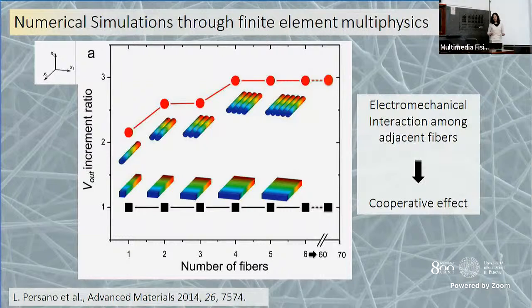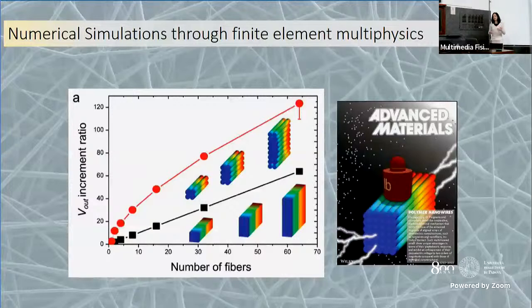And this can be explained as an electromechanical interaction among adjacent fibers, which is named a cooperative effect, that restrains deformation in the transversal direction, thus increasing the transversal strain and thus increasing the piezoelectricity. If we make the array vertically, we can increase even more the voltage output from the material, because here there are two contributions. The first one is the cooperative effect I mentioned before. The second one is that one is increasing the thickness of the material, so it is reducing the stiffness of the material itself.